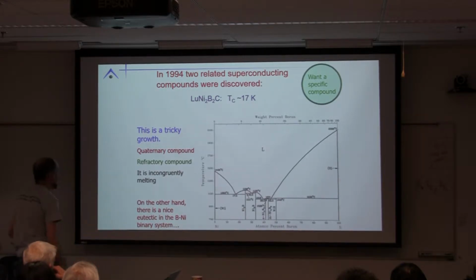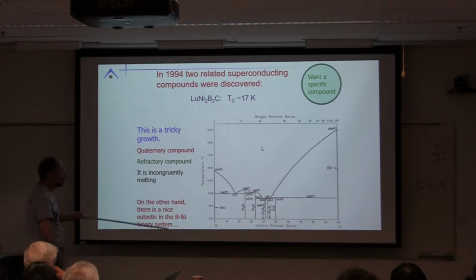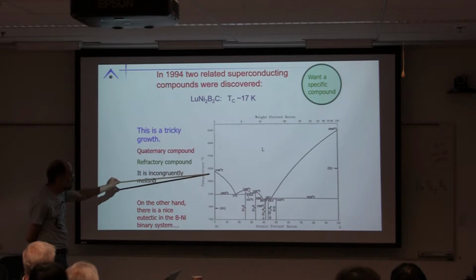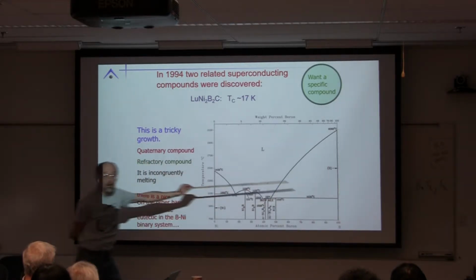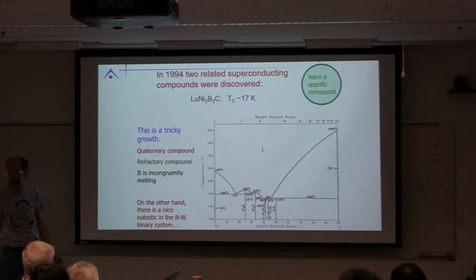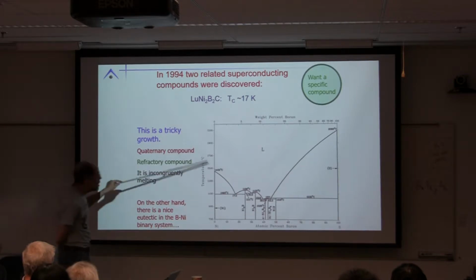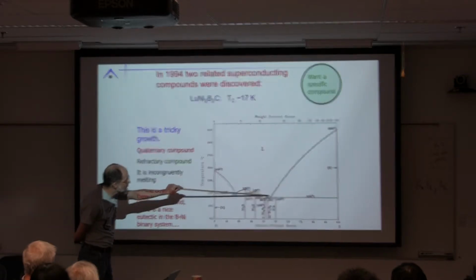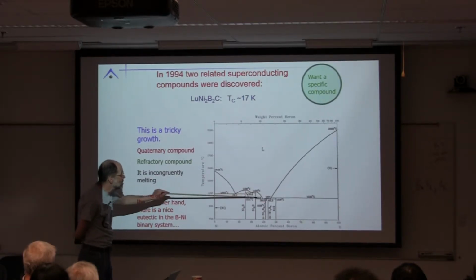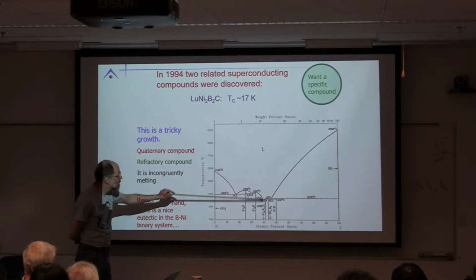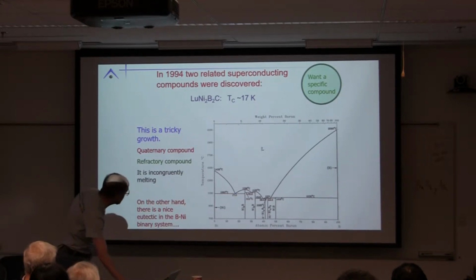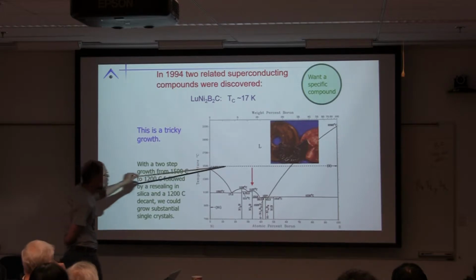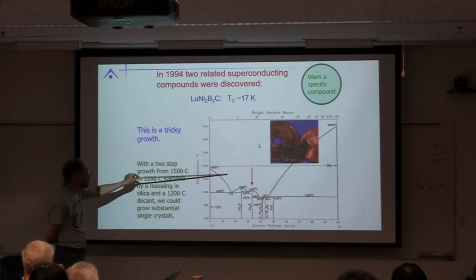On the other hand, after playing around for a while, we realized that if you look at the nickel-boron binary phase diagram, and Helena hopefully went over binary phase diagrams with you nicely, you see that there's this beautiful cascade of eutectics, and you have some eutectics going down to near 1,000, but you can also see that below 1,500, you'll have a lot of exposed liquid to play with.